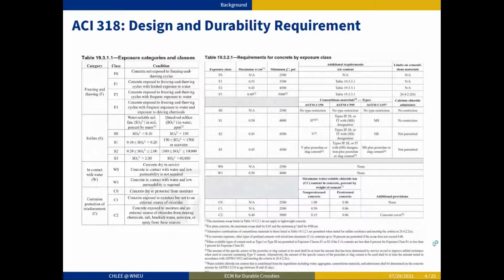AREMA also refers to the American Concrete Institute 318 code for designing the mixture proportions. However, if you take a look at those tables, ACI just provides different exposure conditions for freezing and thawing, sulfate condition, which is related to the delayed ettringite formation, and the contact with the water conditions, which is related to any general chemical attacks, and corrosion protection of the reinforcements.